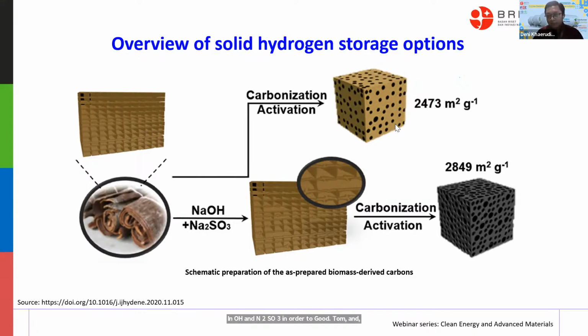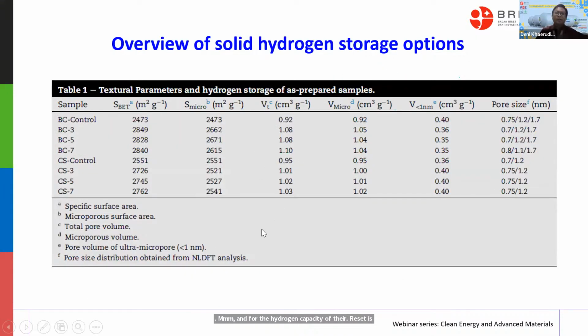So some pores with very high surface area, more than 2,000, even more than 1,500 is a very high surface area. They successfully achieved almost 3,000 square meters per gram. This is very high. Therefore, the hydrogen capacity in their research is very successful. Okay, we can see from this table,